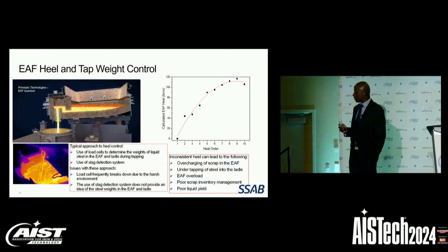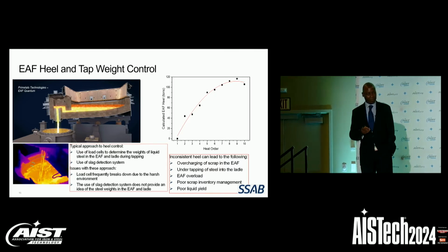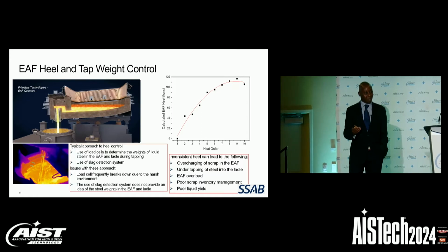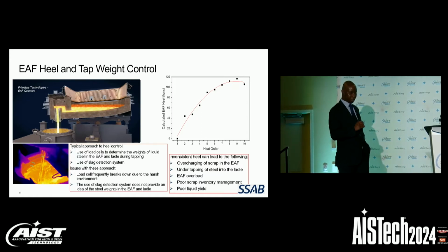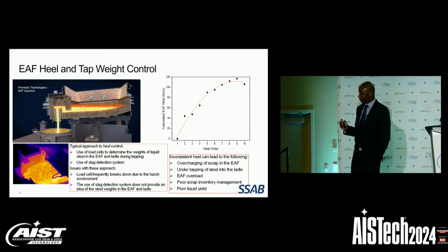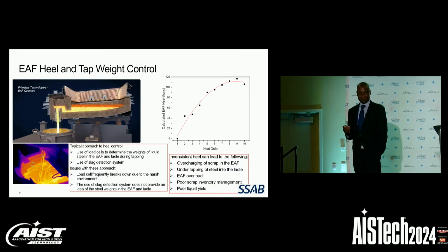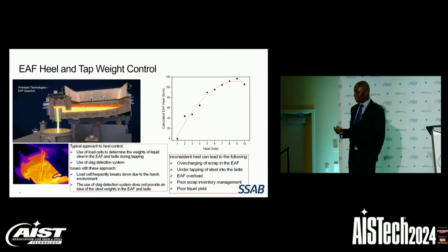The second method is using the slag detection system coupled with eyeballing of the level of the steel in the ladle. This method is not precise. It doesn't give you exact weight of steel in the ladle or in the electric arc furnace. Hence, the heel can quickly run out of control as shown on this chart.